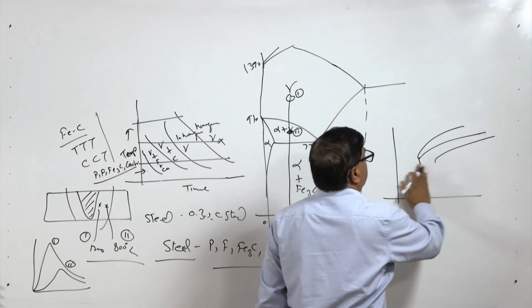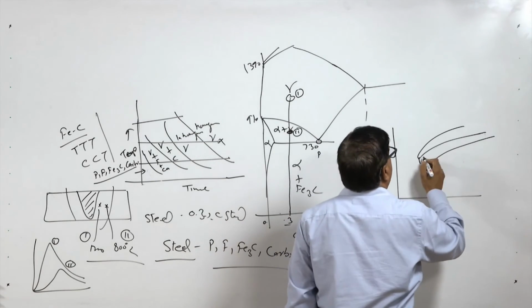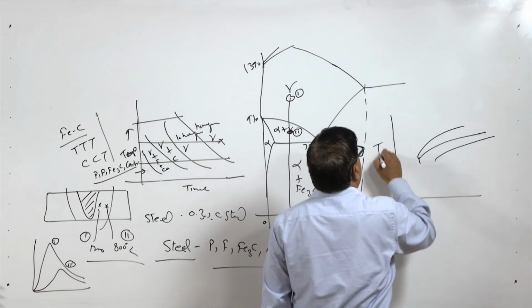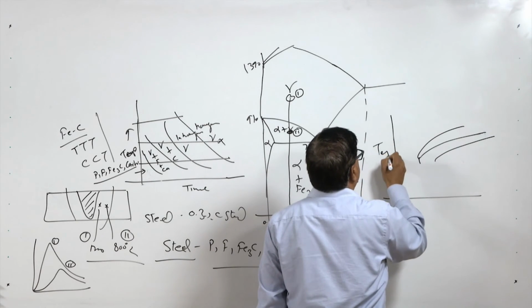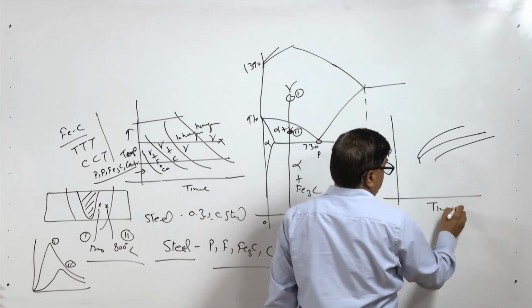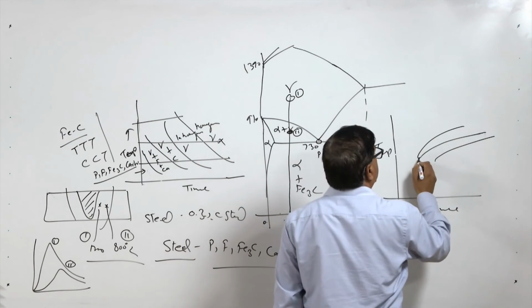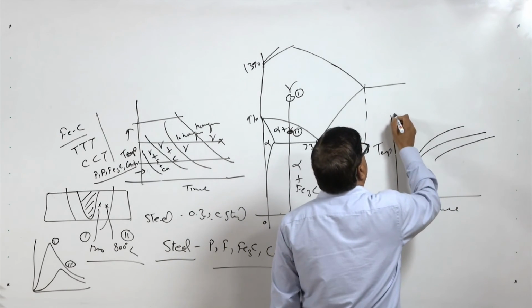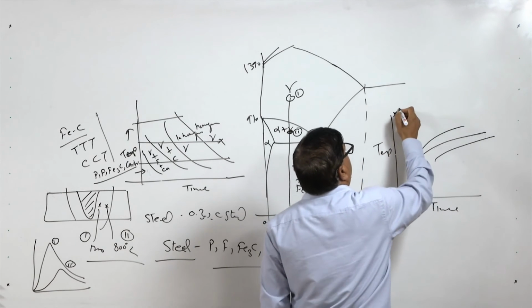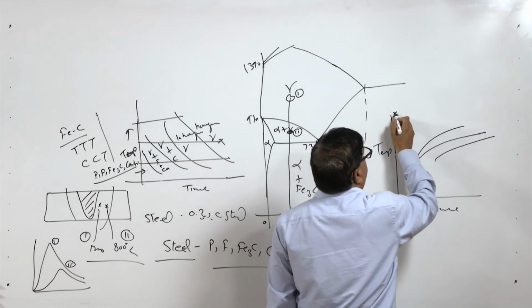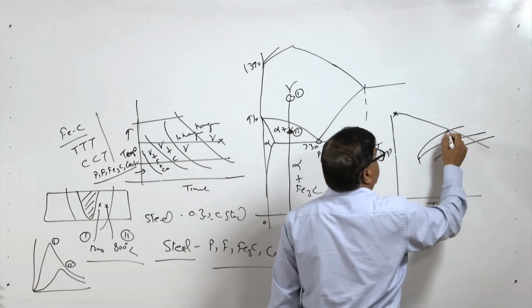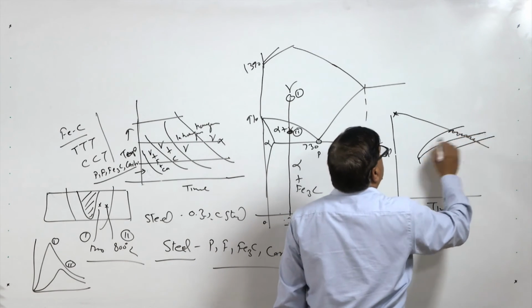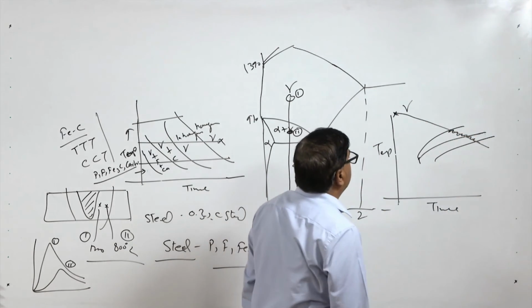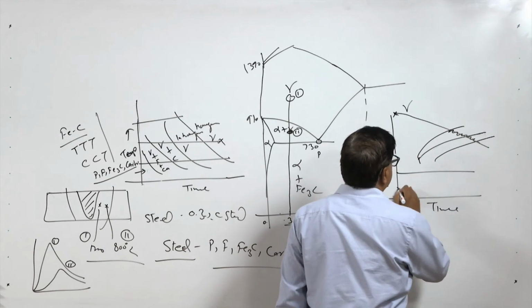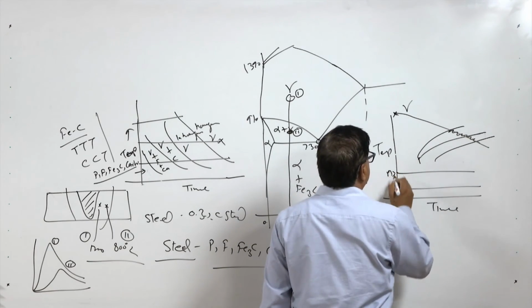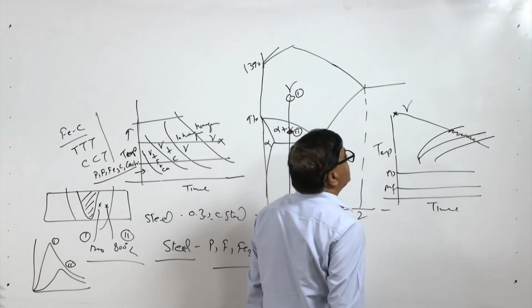So, in the continuous cooling diagram, this is temperature, and this is time. Here this is the nose. Our austenite, which is homogeneous at a high temperature, transforms in these zones as per the cooling rate. So, what are these zones? This is the homogeneous austenite region. Here we will have the Ms and Mf zone, the martensite start and martensite finish temperatures.